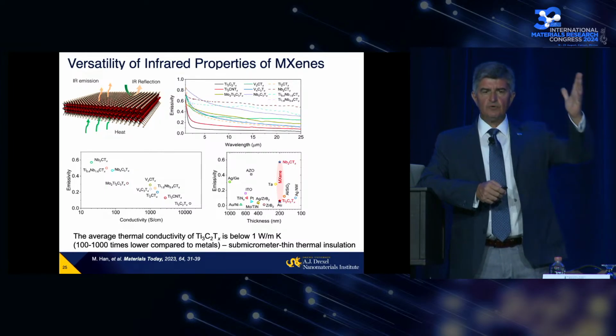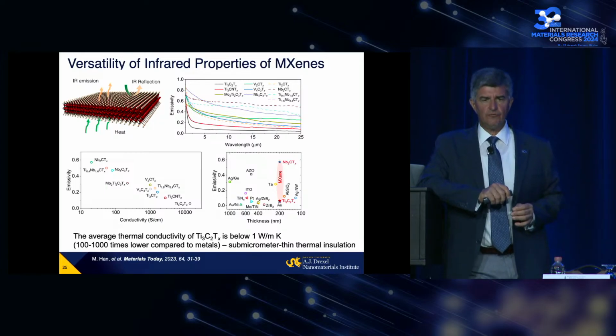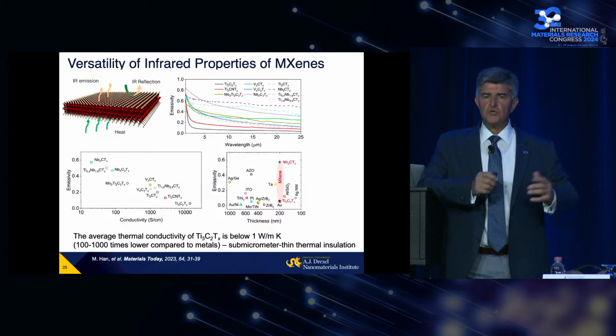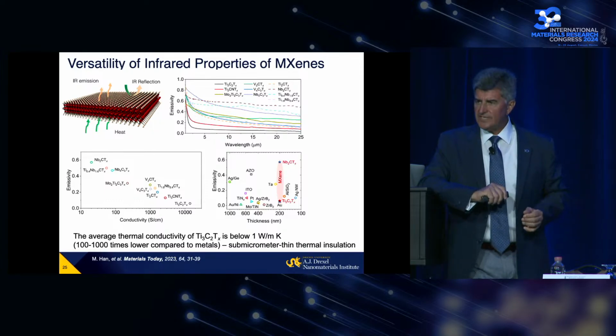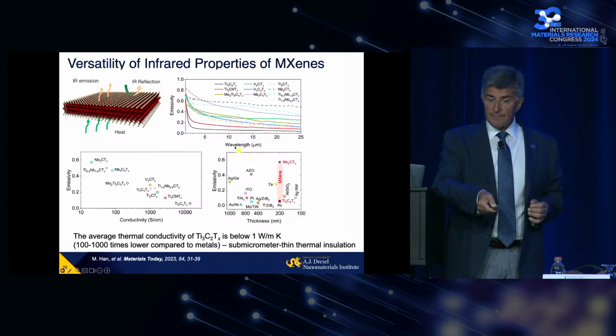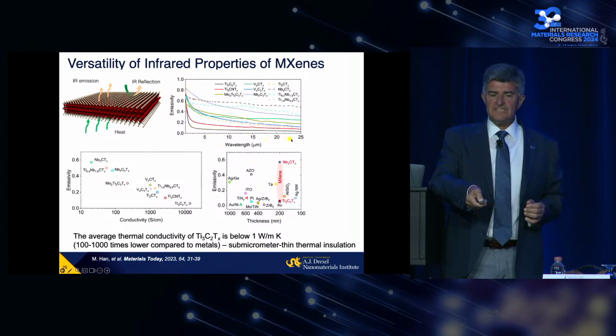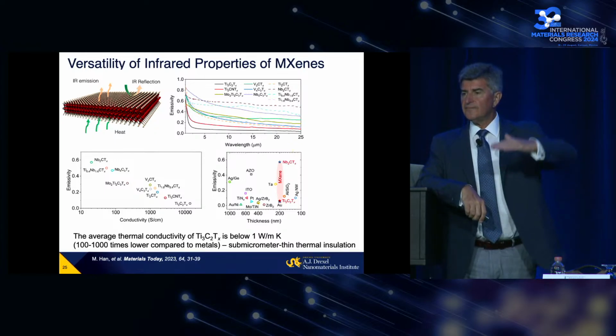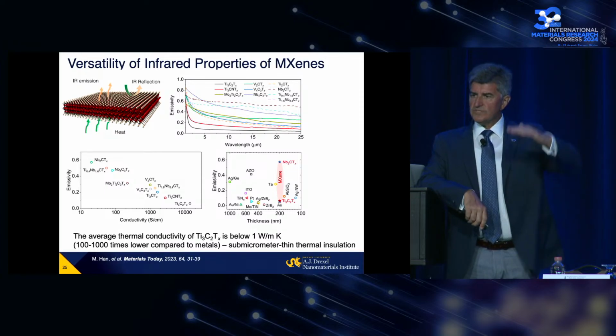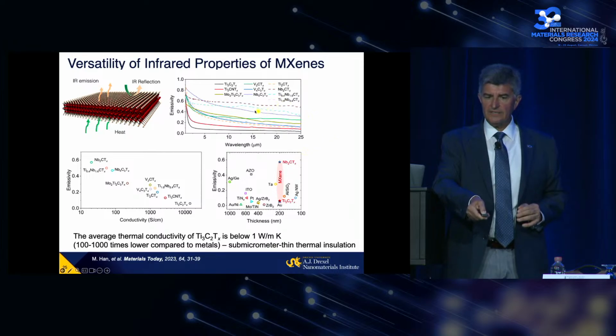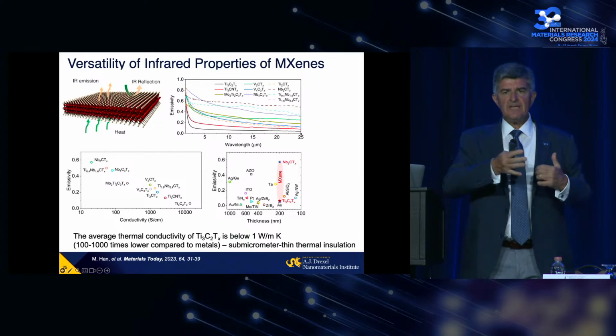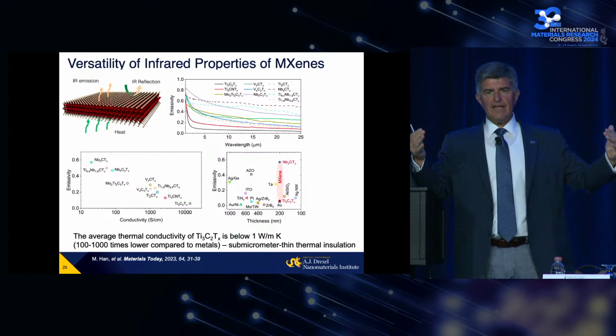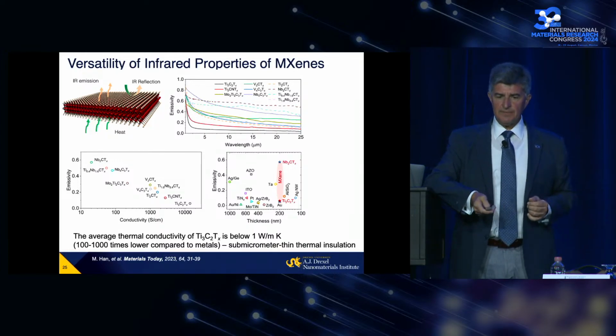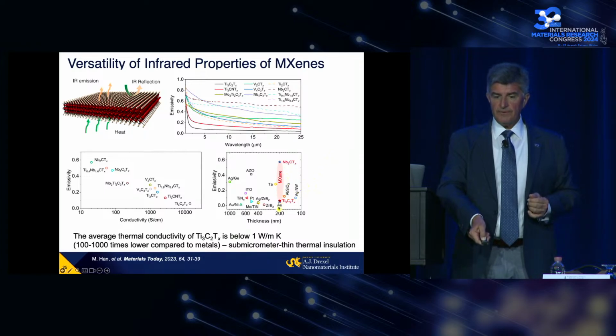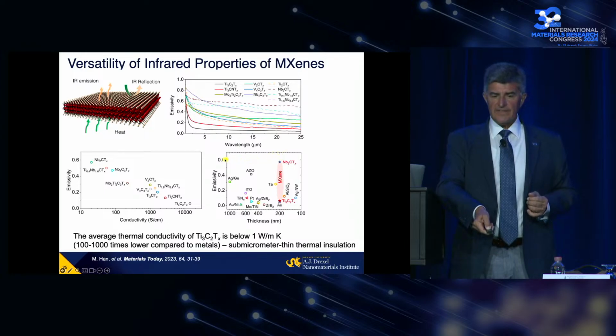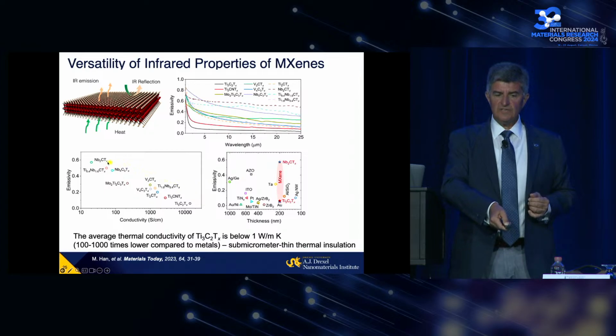For example, I mentioned thermal insulation, and I enjoyed listening to a tutorial today on measuring thermal properties of materials - I'm still a student here, learning. But what's important is that some MXenes, like titanium3C2, have very low emissivity - they're basically reflective as metals and don't emit infrared radiation, so there are no heat losses through radiation. Some others, like niobium carbide, have very high emissivity - they're good for things like space heaters, when you want electrical heaters to emit radiation and heat the environment. So they cover the whole range, from pretty much polished metal like gold to above the majority of other materials in emission, and we can tune and select a material.